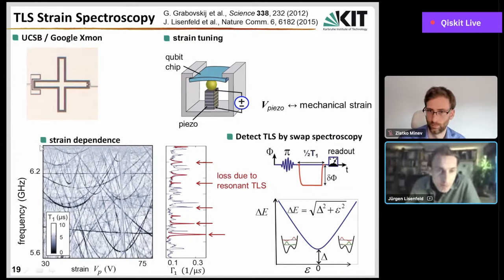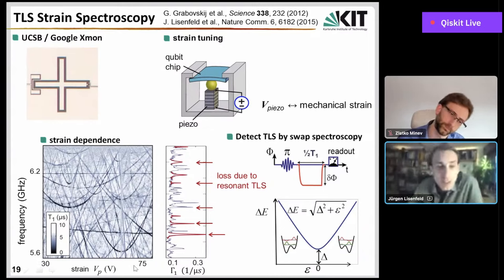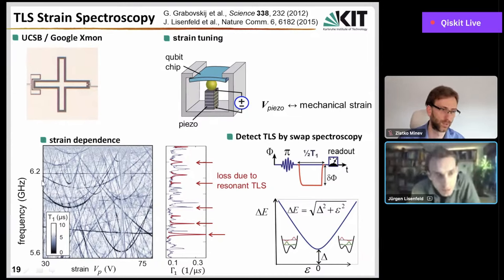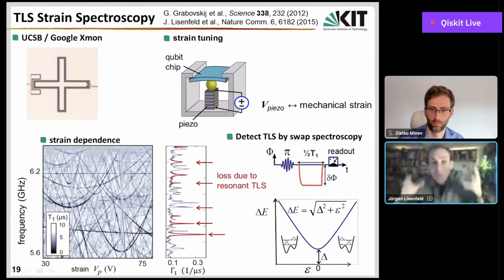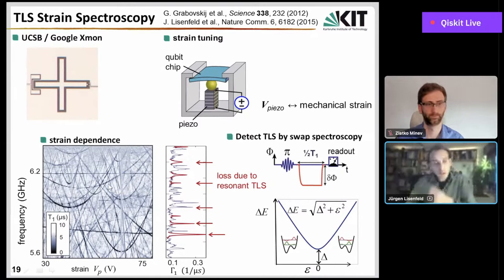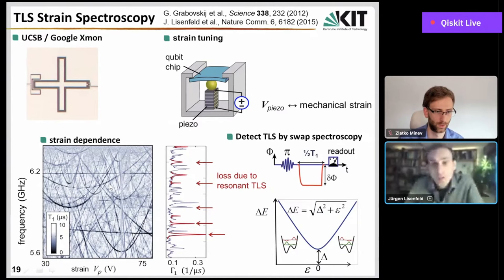And this is a result from such an experiment. Again, you see the T1 time of the qubit color-coded as a function of qubit frequency and applied piezo voltage. You see these dark pixels, where we have bad coherence times, accumulate along these hyperbolic traces. This nicely reveals the resonances of all these individual TLS. We can really say these are TLS because we find these hyperbolic couplings to the mechanical strain, and everything seems to be nicely explained by this double potential model, by the standard tunneling model.